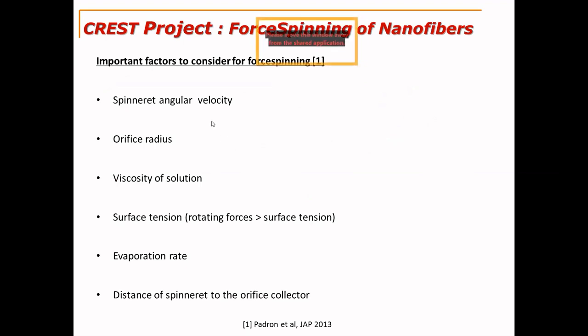spinneret angular velocity. Suppose the spinneret rotates at a high speed, the polymer solution will get deposited on the collector plates and it will not get solidified before it reaches the collector plate. So the crystallinity of the fibers decreases and the properties of the fiber deteriorate because it will cause molecular defects in the nanofibers. So we should pay attention to the spinneret angular velocity. And also if the angular velocity is very low, the fibers will not get generated because there will not be enough rotational force to generate the fibers. So we should pay attention to the spinneret angular velocity while we use force spinning of the nanofibers.